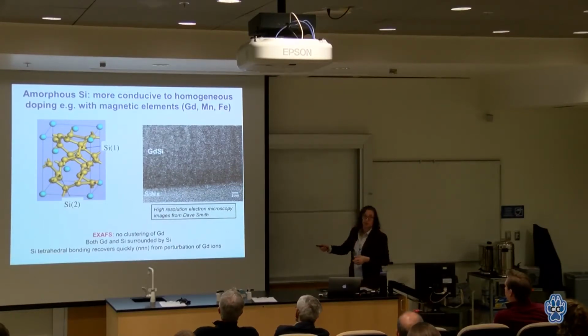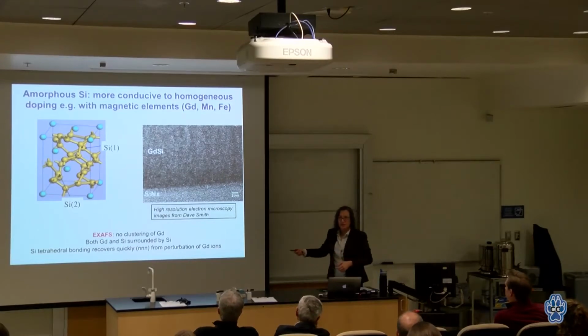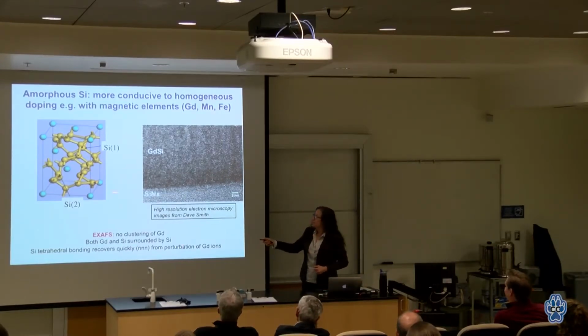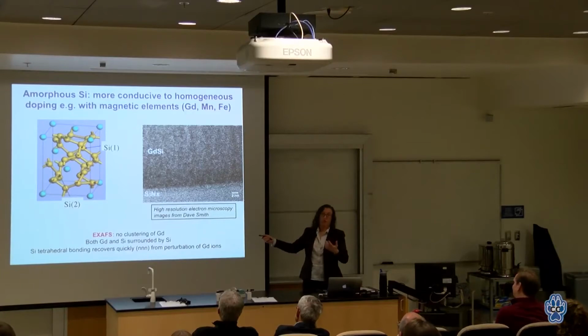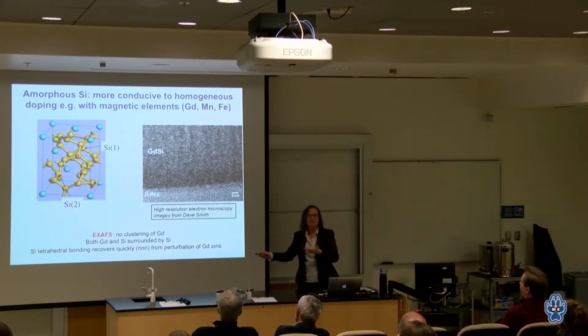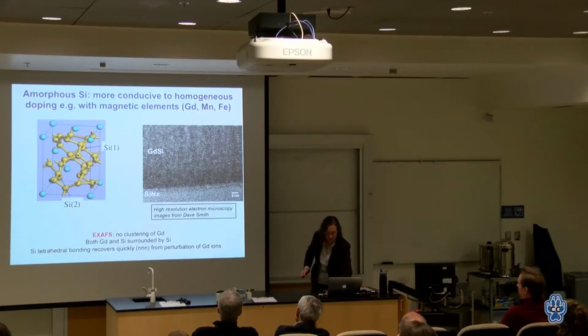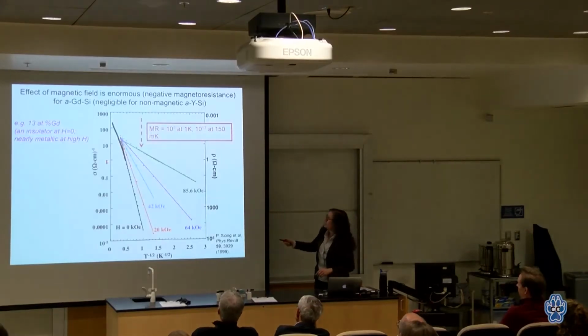So I decided I wanted to see what happened if I put real magnets in here. That was the genesis of this project of putting rare earths in here. Gadolinium has an enormous magnetic moment. So we tried putting gadolinium in. And indeed what happened was actually quite interesting.